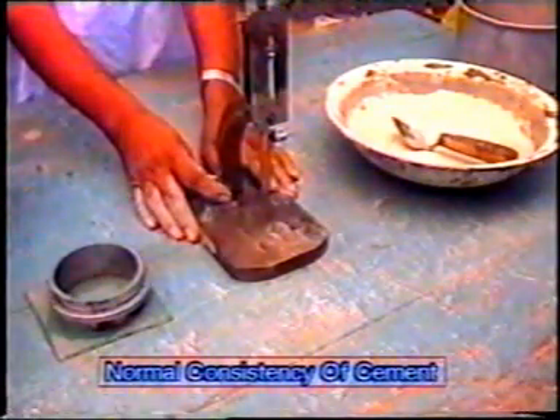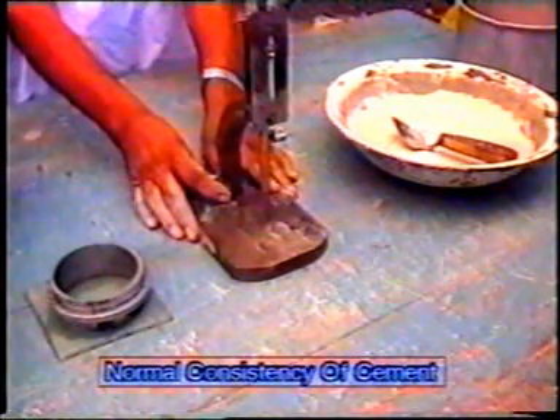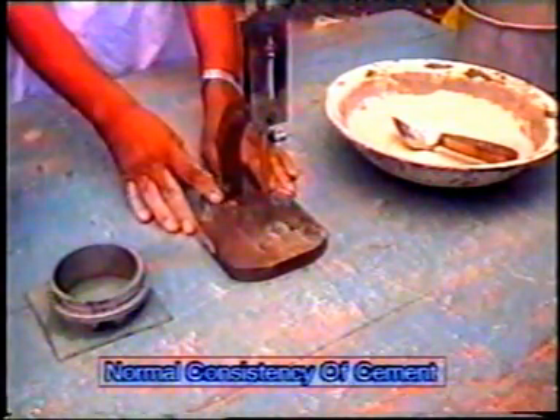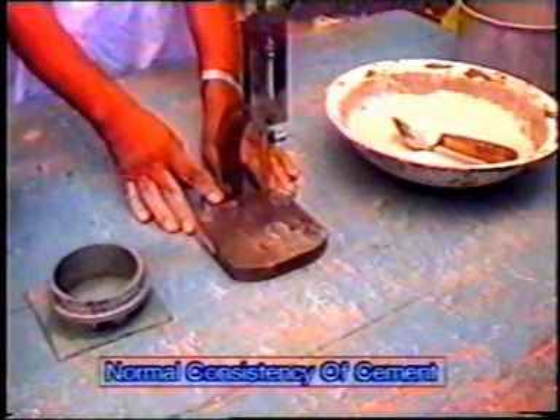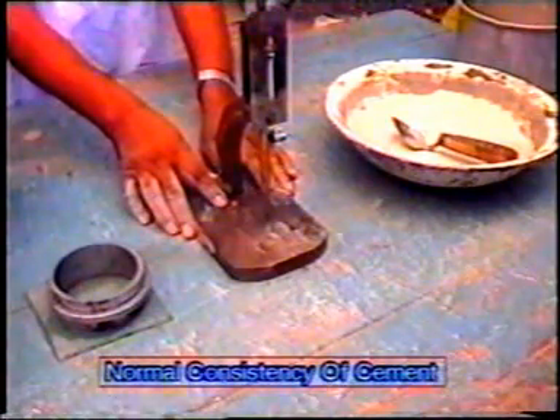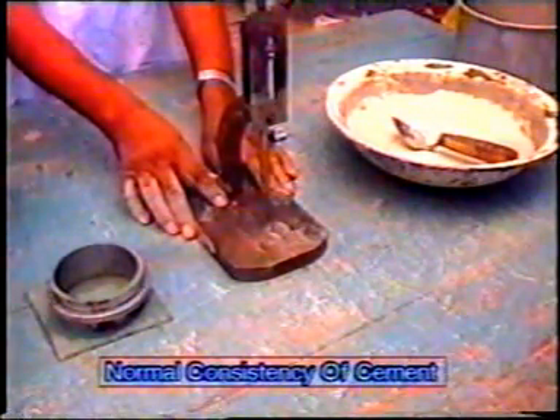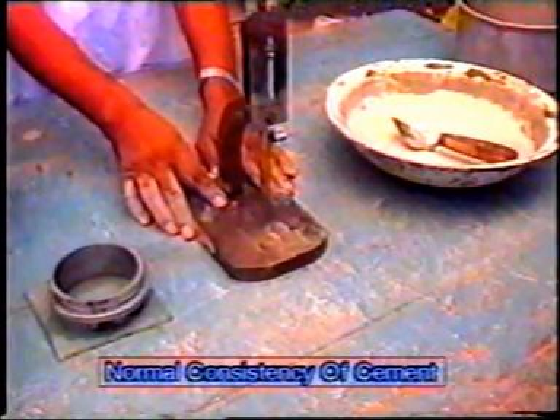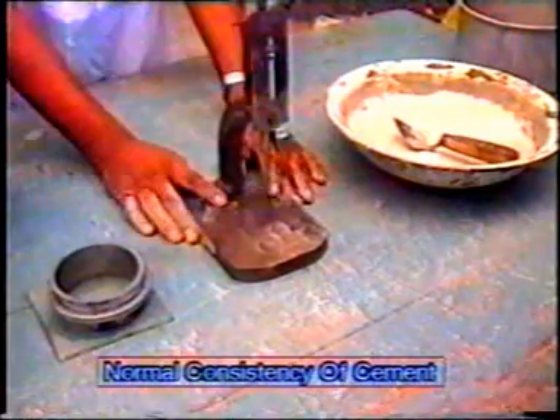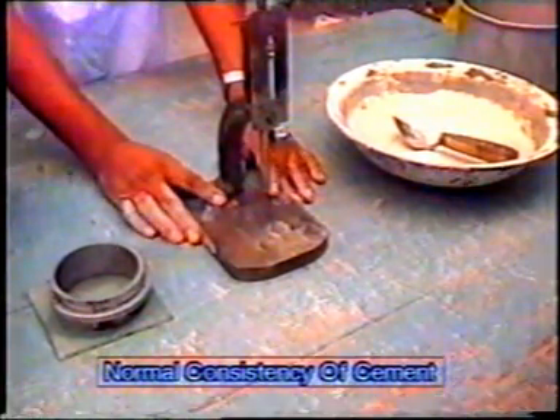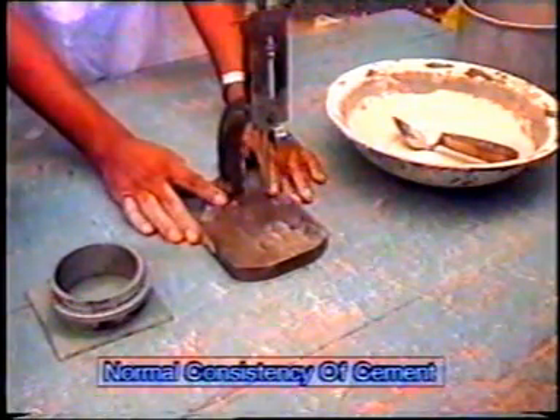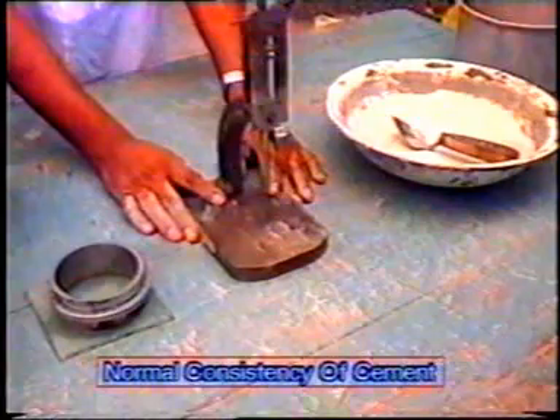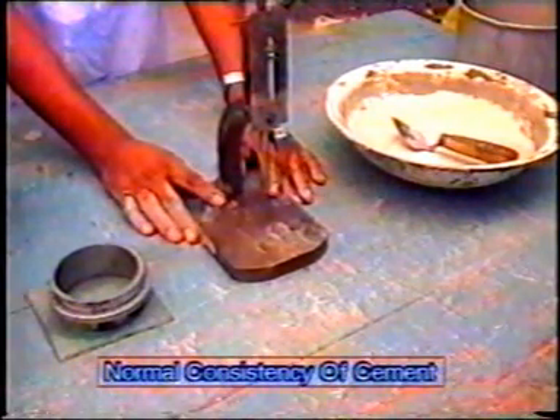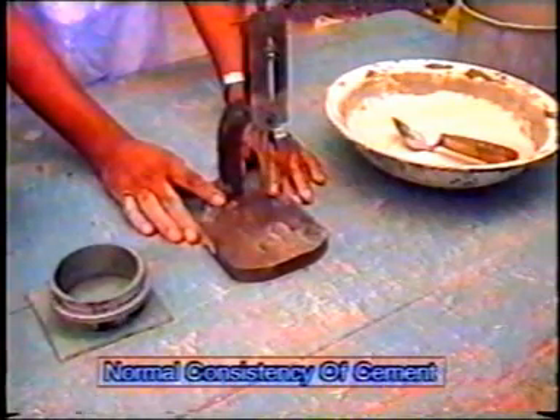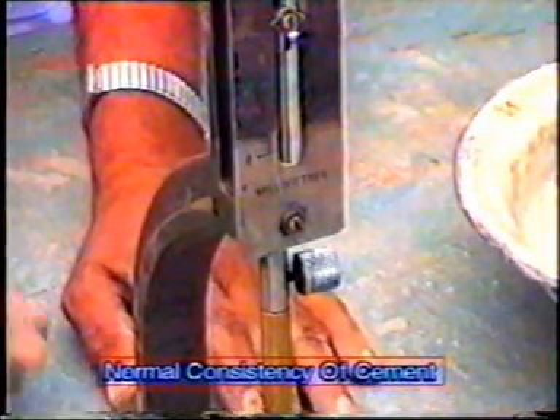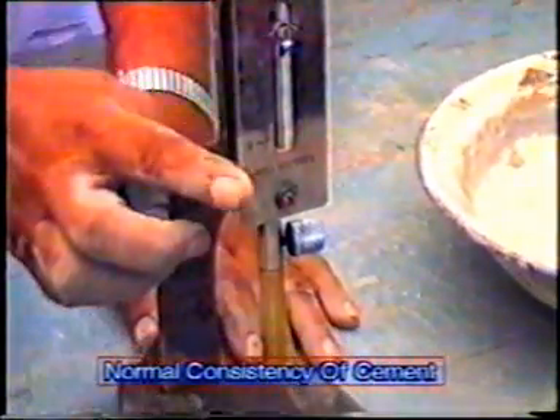The setup now being looked at is for determination of normal consistency. Normal consistency of cement may be defined as that percentage of water which allows the plunger to penetrate to a depth of 5 to 7 mm from the bottom. This test is a prerequisite, as the quantity of water to be used for different tests is based on this normal consistency value only. Now let us see the apparatus required for normal consistency.